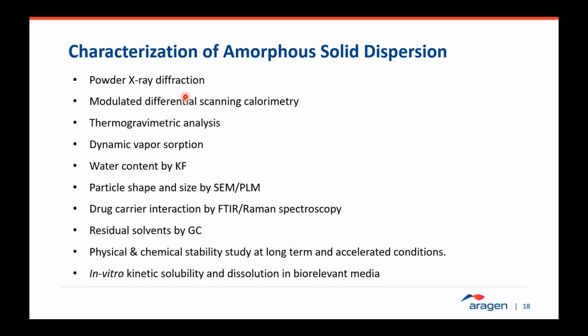So typical characterization includes the powder X-ray, modulated DSC, TGA to understand any solvent presence, and hygroscopicity by DVS, water content, particle shape and size by SEM and PLM. And drug and polymer interactions are studied through FTIR or Raman to understand if there is any interaction or their physical coexistence in the matrix. And the residual solvents estimation by gas chromatography, and physical and chemical stability at long-term and accelerated conditions with the protection of humidity and without protection. And the last important piece of the data is in vitro kinetic solubility and dissolution in biorelevant media.